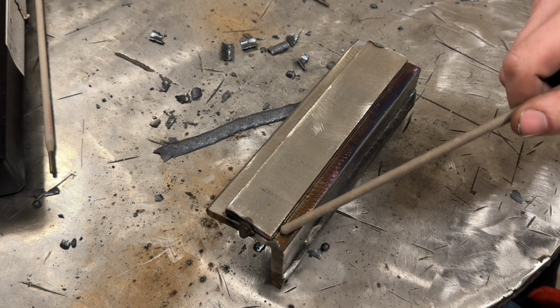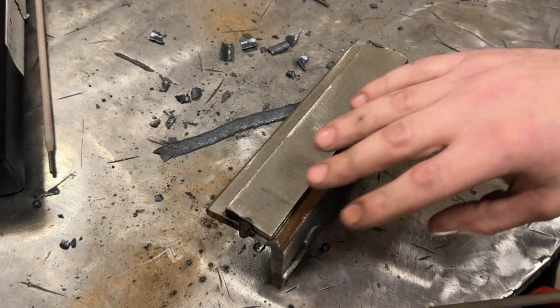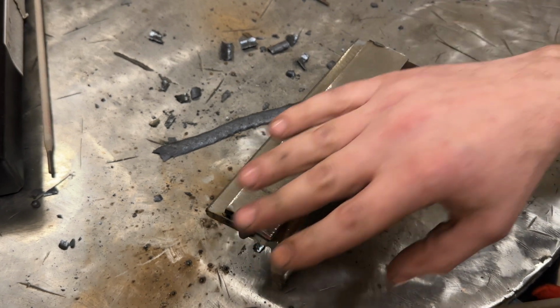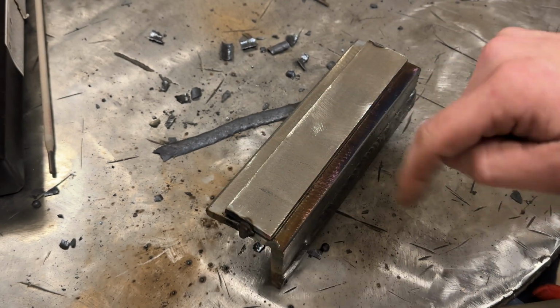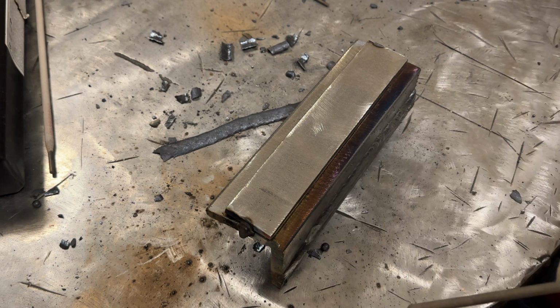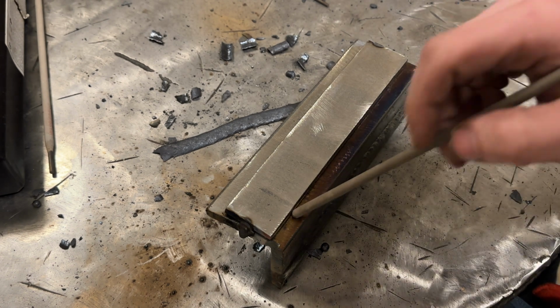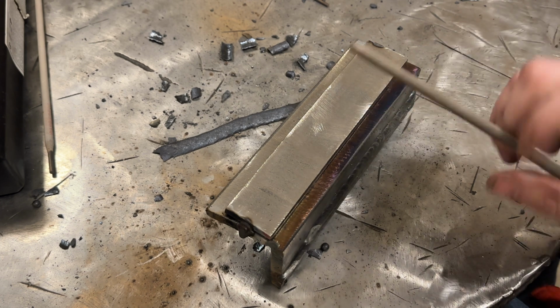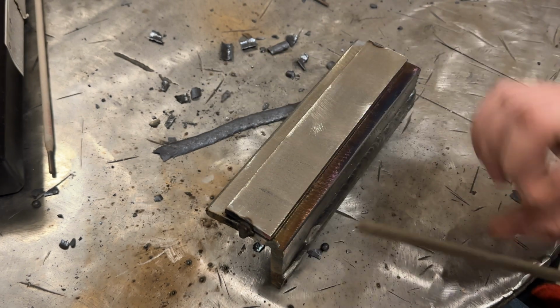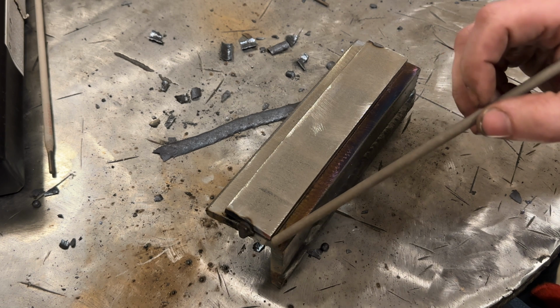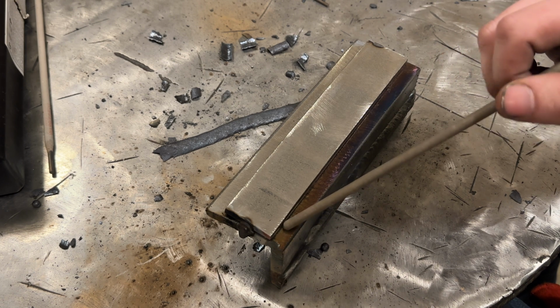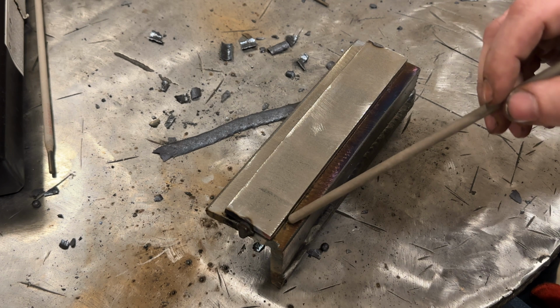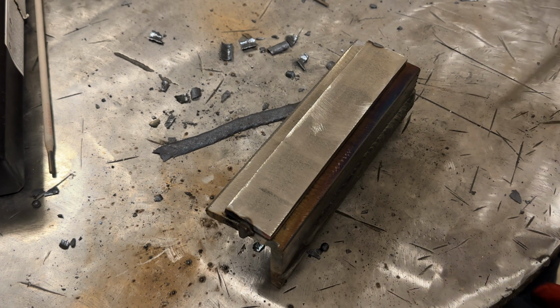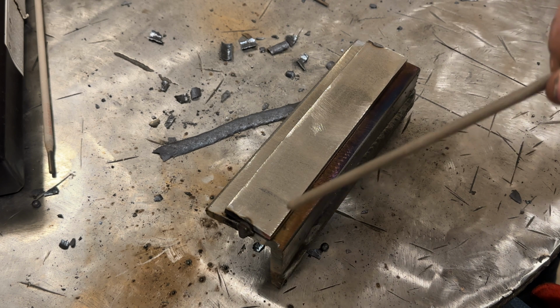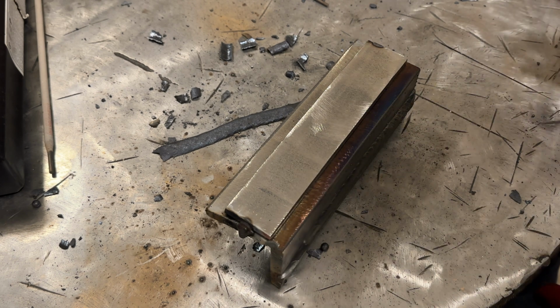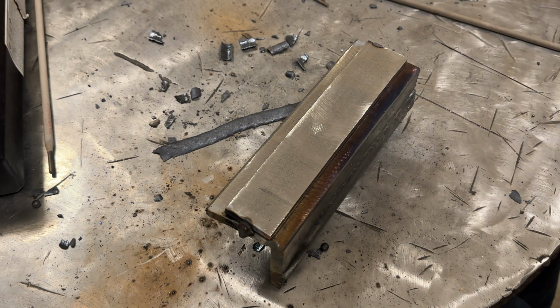You're going to want a fairly steep drag angle to try and get what little bit of arc force this has to keep that molten puddle pushed that way rather than having it come in front of your rod, because you're going to get slag entrapment terribly with that. And you're going to watch that puddle really swirl around and kind of do its own thing. You just have to trust that if your travel speed is good and you're feeding enough rod, that everything is okay, because it's not like 7018, it has a really distinguishable puddle. This simply doesn't. So there is a little bit of trust involved in getting this to work right.